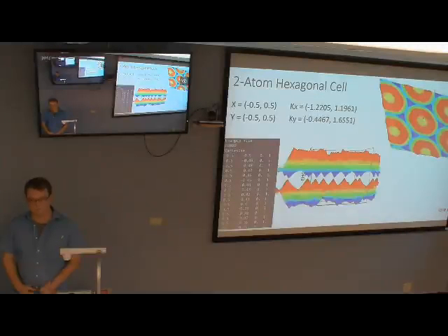The picture on the bottom, is this some kind of side view? Yep, it's a three-dimensional structure. This is just looking at it from the middle, and then the other one is looking at it as a contour plot. So you have a little bit of a gap there, right? They don't touch. True. Well, from the K-points that I calculated, they do not touch. That could mean that my grid isn't dense enough. I didn't calculate a lot of points, so I don't know. It could be any number of things.